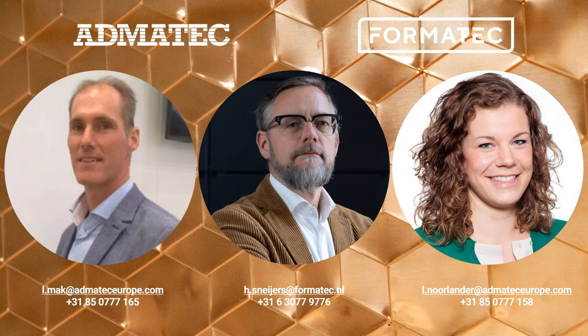Okay, thank you, Laurent. There is a question in Dutch, which I will translate. What is the layer thickness of building a product? So this is selectable, and it's also related first on the possible depth of cure you can obtain. So how far can the light penetrate into the material? Second, it is depending on the accuracy you want to have in your print. And typically, we use layer thickness between 10 micron and 30 micron when printing in copper.